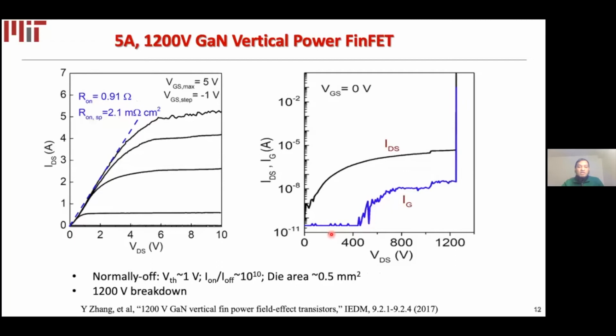Using this approach, a few years ago, our group demonstrated a 5 amp, 1200 volt vertical GaN power FinFET on bulk GaN substrates. These devices showed normally-off performance with a threshold voltage of 1 volt, an on-off ratio of 10^10, and 5 amps current in an area of 0.5 millimeter square die size.